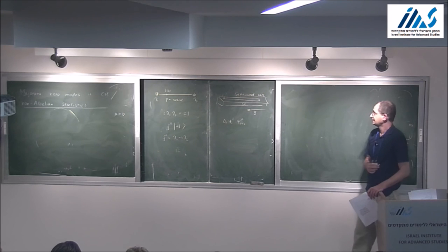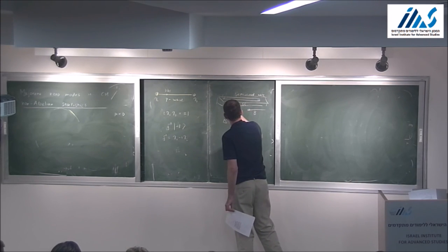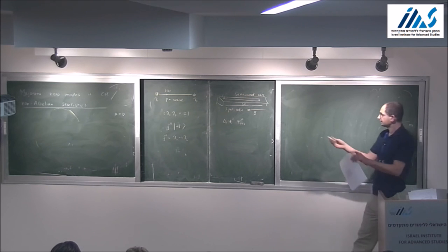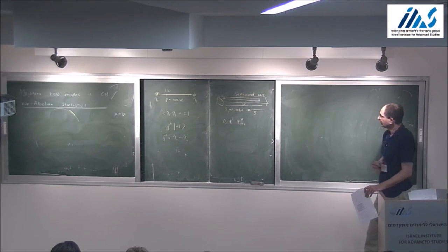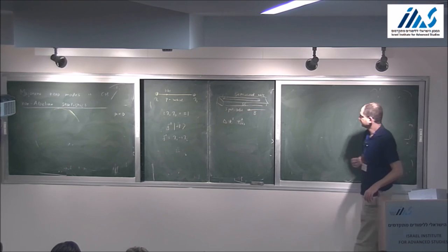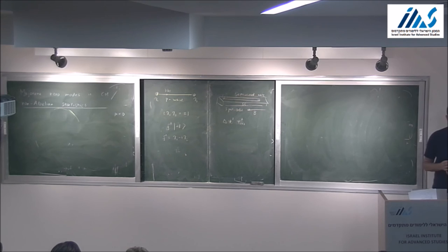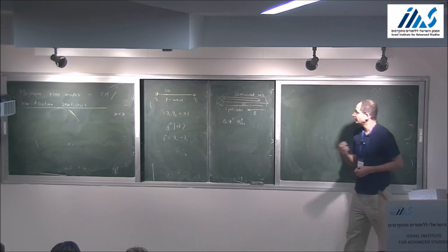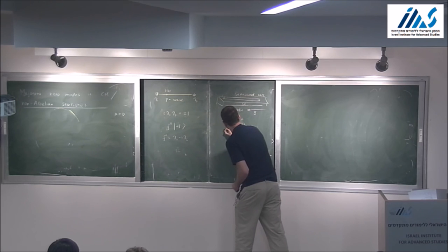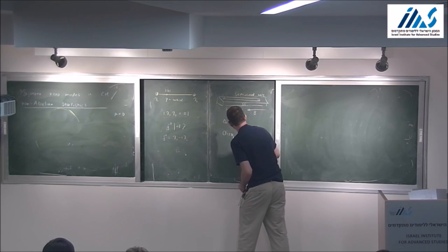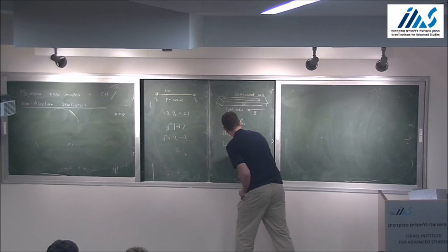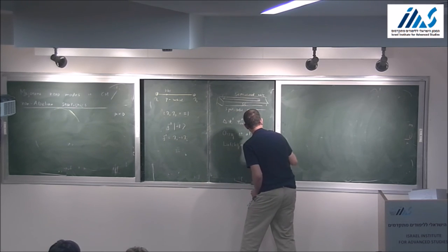It turns out, and this was really the breakthrough in this, the third ingredient that you need is spin orbit coupling. So that needs to be strong in this quantum wire. What that does essentially is it locks the spin of the electron to its momentum, and then when you apply a magnetic field, the spins don't actually become completely parallel to each other. So by combining these three ingredients, you can realize this phase as a matter of principle. This was pointed out by Yuval Oreg and company, and at the same time by Roman Lutchyn, both in 2010.